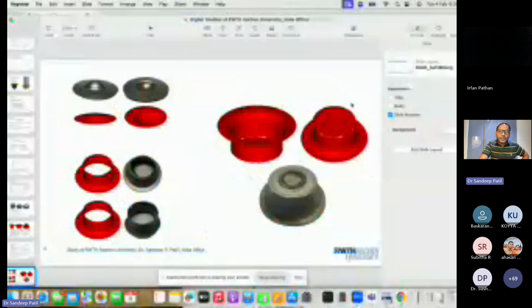Then we also carried out a little bit more extreme pressure than the 150 bar. Then we found that there was damage, and you can see it here. Interestingly, this damage happened here, and we could predict it at the sharp corners at the bottom. Then we went again to a high extreme pressure, where the blank at the bottom almost flew away. This is what we also observe in the numerical simulation.